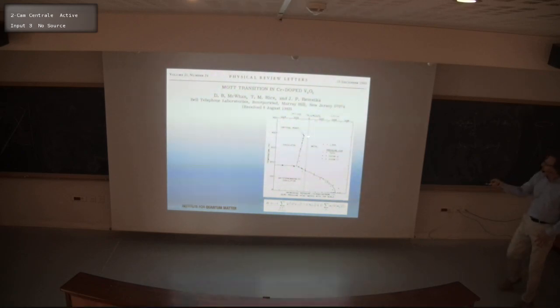And there you do have this first order phase boundary between a paramagnetic insulator and a paramagnetic metal. And the crystal structure is maintained. So it really is the character that we expect for the so-called Mott transition. It's not a Slater transition, it really should be a Mott transition.